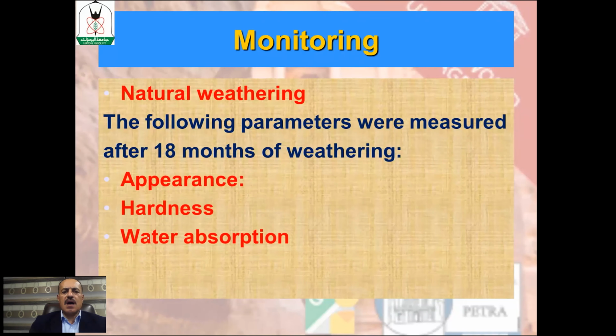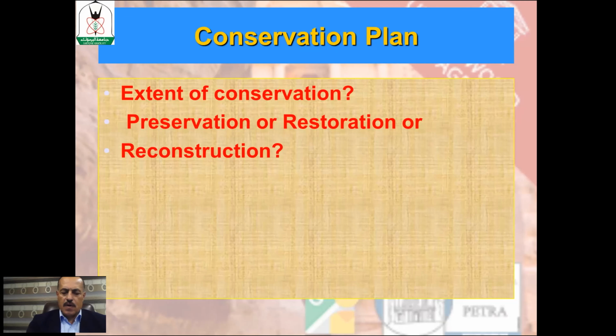So we monitored the appearance, the hardness, and the water absorption of these mortars over a period of 18 months. And after we had all these results from the laboratory and the field, and after a true and real understanding of the weathering forms and causes of the weathering, we reached a state where we could start thinking of proposing some conservation intervention. As you see, we needed about 3 years of laboratory and field testing before we could really answer the question about the extent of conservation first, what to do in terms of conservation, whether to adopt a preservation or restoration or reconstruction, or most likely a mixed approach, which combines all of these together.